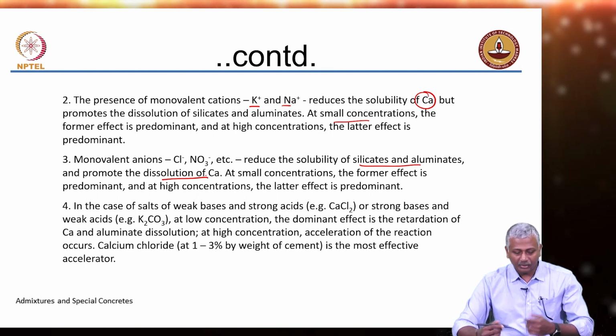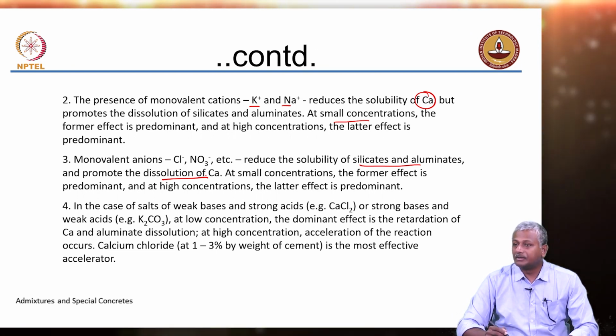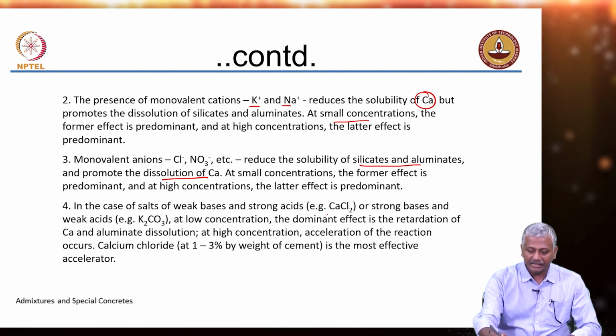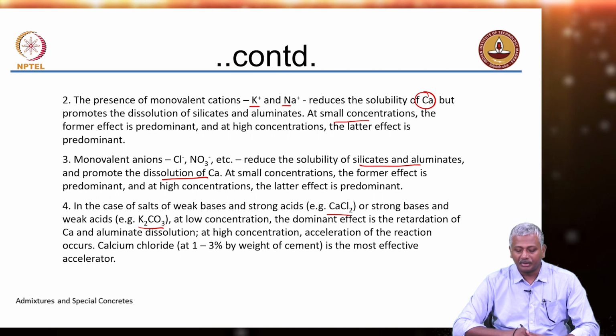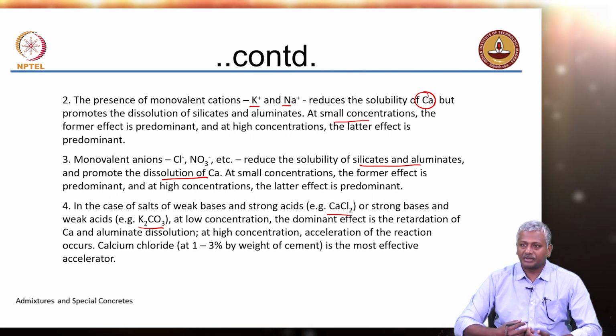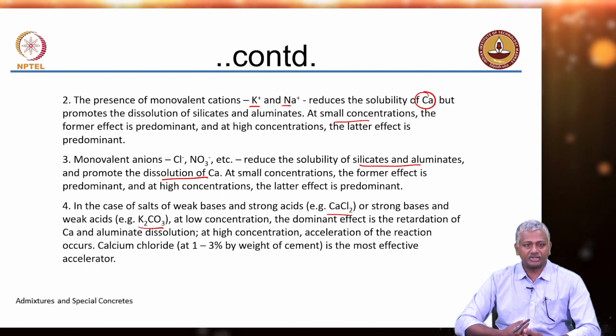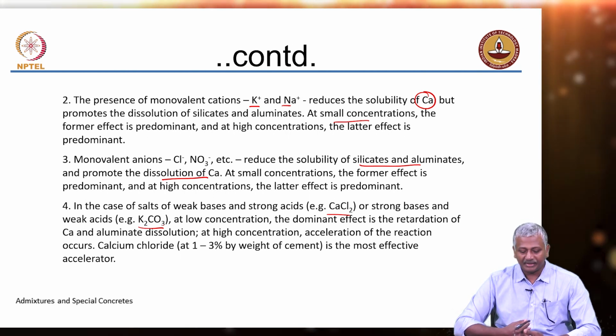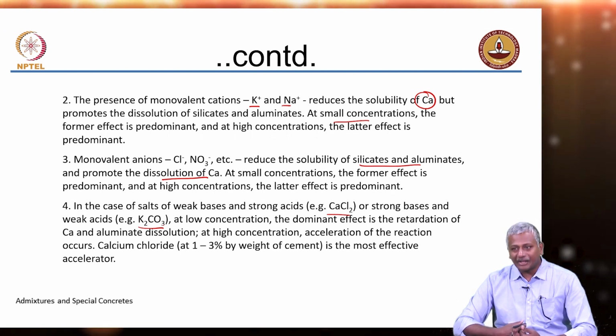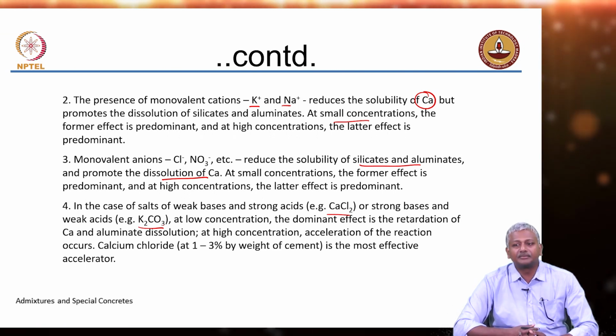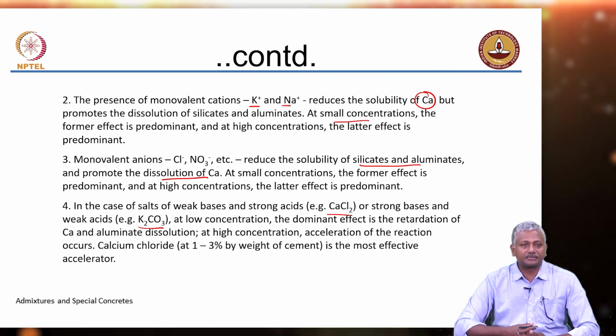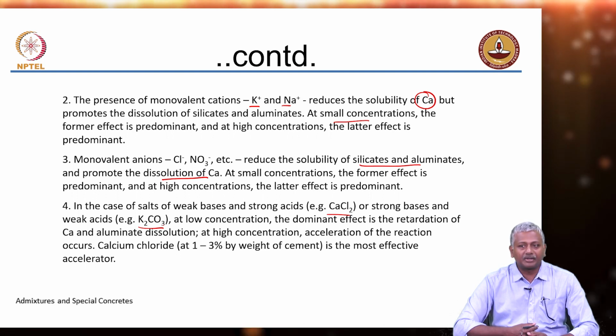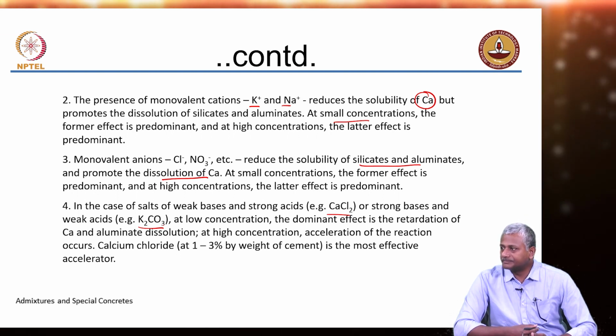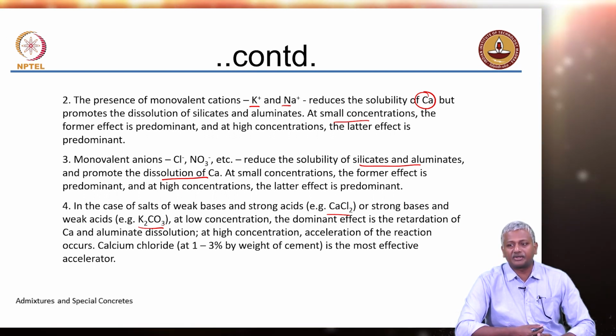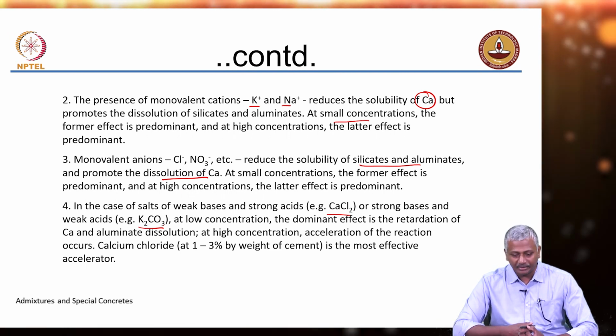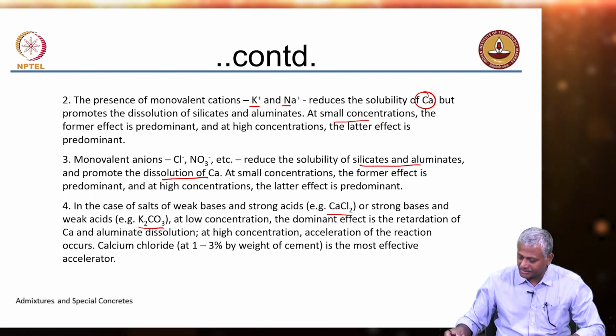Obviously we are using mixtures of ions, so, calcium chloride or potassium carbonate and so on. When you have a low dosage, the dominant effect is the retardation. At high dosages, the dominant effect is the acceleration. But calcium chloride is an accelerator that cannot be used in reinforced concrete because chloride will induce corrosion, right. So, we have to look for non-chloride chemicals. Calcium nitrate is an option. Calcium nitrite is also an option because it also acts as a corrosion inhibitor, which we will look at later. Right now, we will stop because we are out of time for today's class.